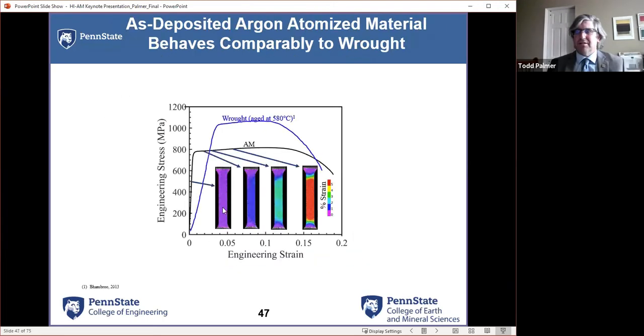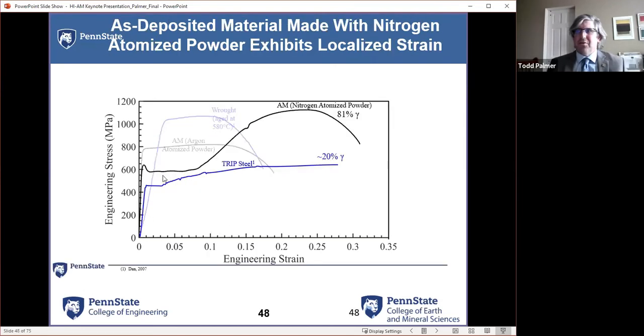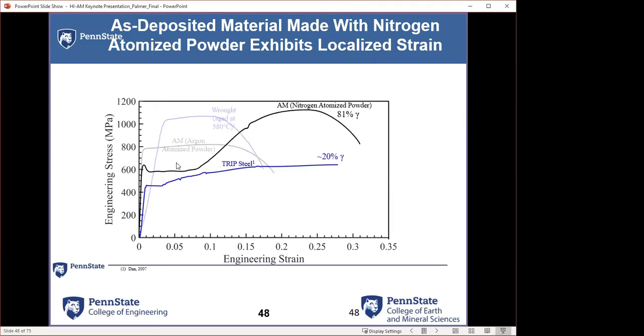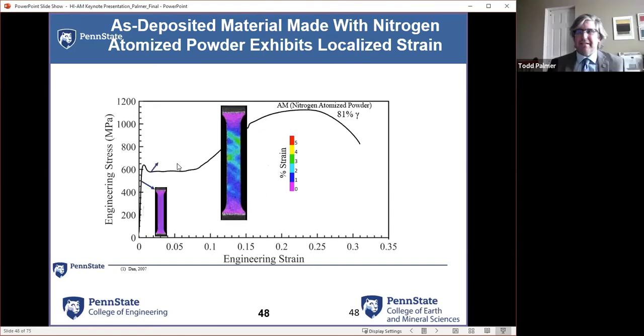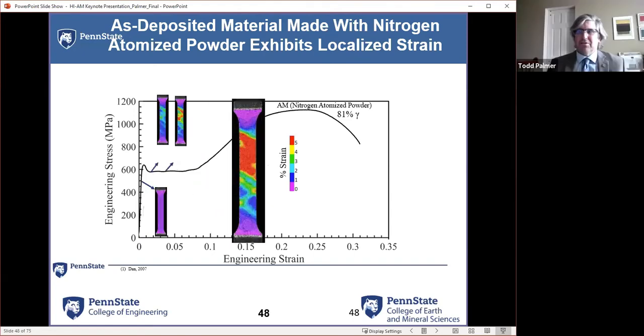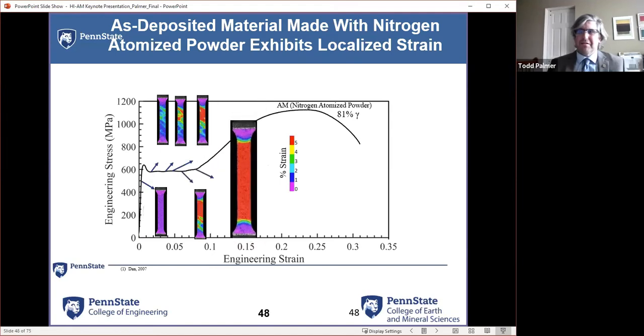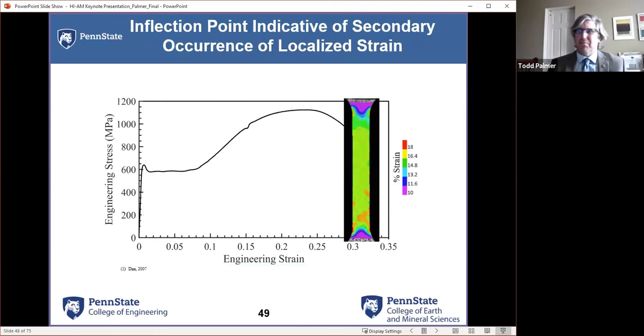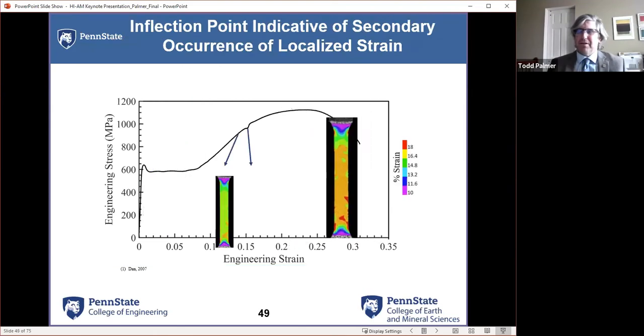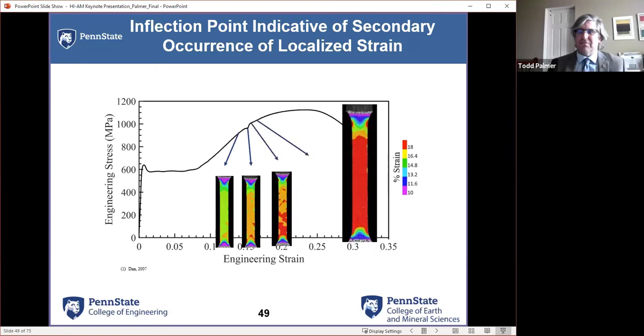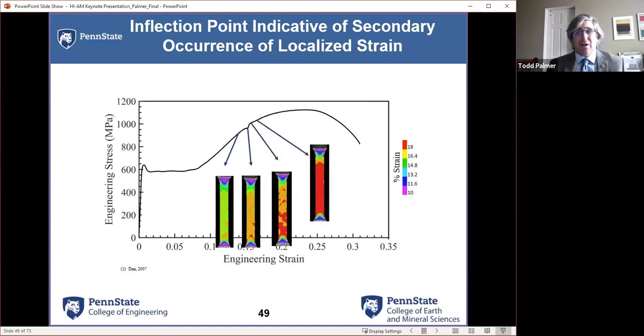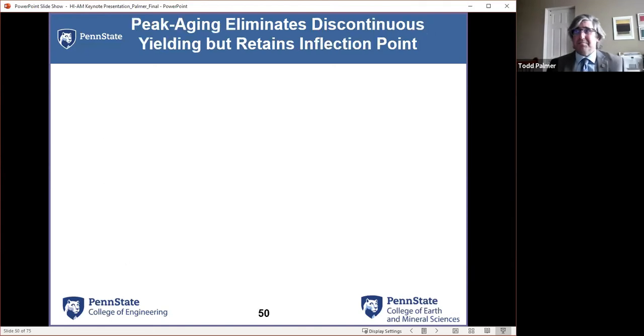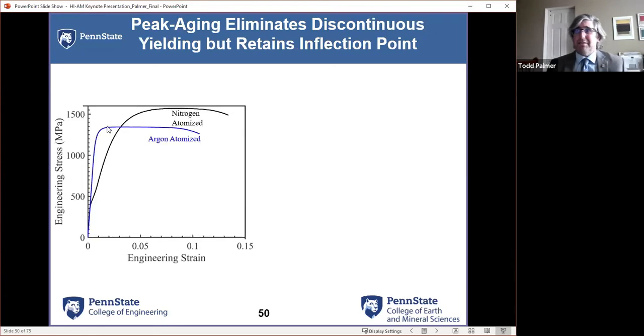But if we do digital image correlation of them, we tend to see fairly uniform strain fields. Now, let's go to the nitrogen atomized powders. That retained austenite is going to give us the fun stuff here, where we start looking at this interrupted yield point, and we start seeing the presence of Luder's bands there. And then as we go up, we see it again. So we see a couple places within the curve where we're actually starting to convert that retained austenite through strain-based processes into martensite.